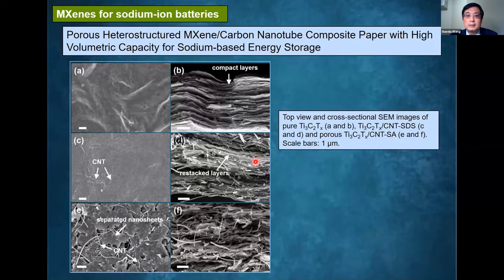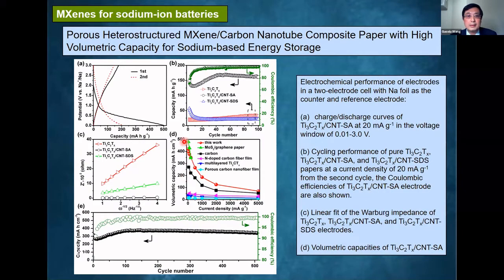So this is a cross-section SEM view. You can see we obtained the sandwich structure. The MXene nanosheets sandwiched by carbon nanotubes prevent restacking of individual MXene nanosheets. And when we apply these materials as the anode materials in sodium-ion batteries, we achieved quite high specific capacity around 350 milliampere-hour per gram, and we achieved more than 500 stable cycles.